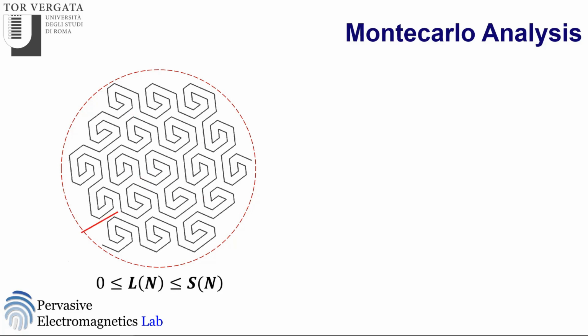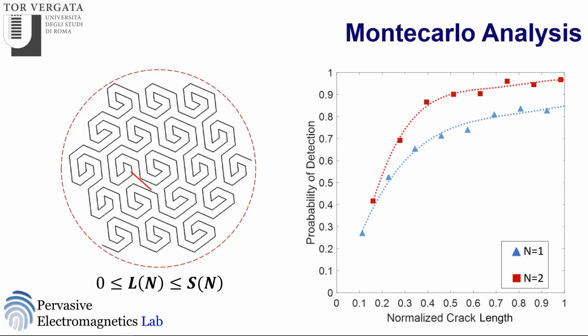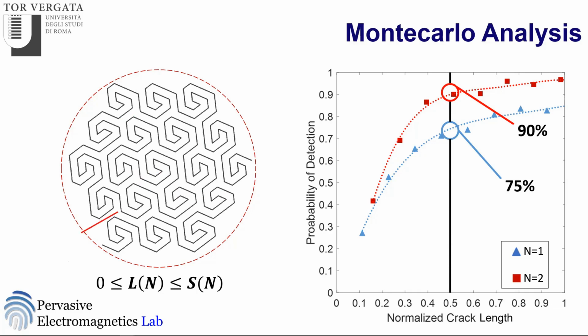Choosing a wide population of segments having different lengths in the following range, it's possible to get the probability of detection of the related curve. As expected, increasing the iteration order of the curve n, thus the space-filling density, allows a higher probability of detection of an arbitrary length crack. For instance, assuming the occurrence of a half crack length, the probability of being detected goes from 75 to 90%, passing from order 1 to order 2 of the same curve.